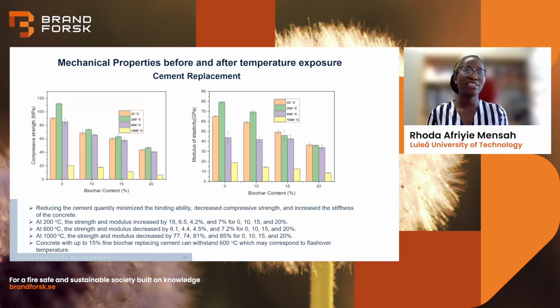So after the fire test, we performed mechanical and tensile splitting tests for both the cubic and the cylindrical samples. On this slide, we have the results for the cement replacement samples. We saw that reducing the quantity of cement and increasing the biochar content decreased the compressive strength and also decreased the stiffness of the concrete. The notable observations we made were that at 200 degrees Celsius, we saw a significant increase in the compressive strength and also the modulus of elasticity.